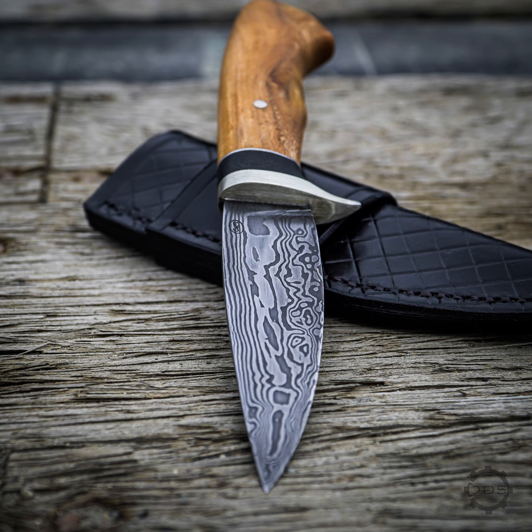But I've used 1095 extensively, and I have heat treated it to where I can get a blade razor sharp, hammer it through a piece of brass rod, and it'll still shave hair. Then I can flex it in a vise to 90 degrees, and it comes back to true, with no cracking and no edge deformation. So it's a good steel type, but if you're looking for certain qualities in a steel, you might look at other steels.